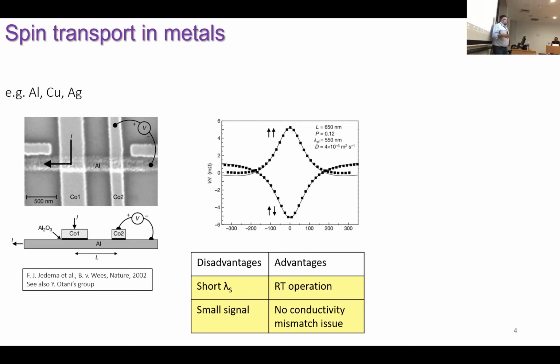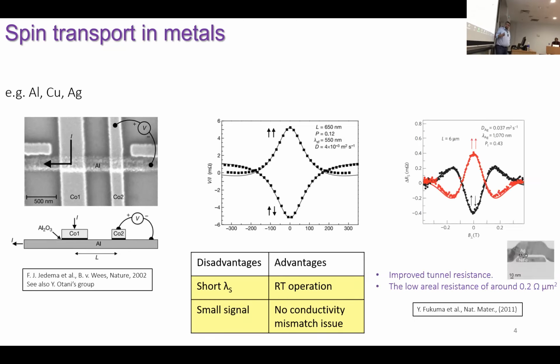So if you want to do spin transfer torque studies, etc., with the pure spin current, you will need much more spin accumulation in your channel. So they might not be the best material choice. And of course, over the years, there has also been quite some improvement in metal spintronics. For example, by improving the contact interfaces, a group in Japan managed to increase the spin relaxation lengths up to 6 microns, which was quite good in terms of the spin transport materials.